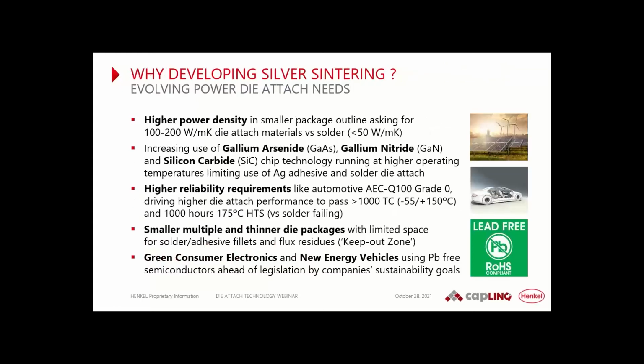So apart from lead-free, as I mentioned already, higher power density is another driver. Also the change in chip technology, moving to gallium arsenide, gallium nitride, silicon carbide running at higher temperatures. Then solder is getting marginal on reliability. And reliability, like Chris already mentioned, automotive, higher temperatures, is also one of the key reasons to go to sintering, because most solder joints cannot pass 1,000 cycles automotive. And then we indeed have also smaller packages with limited space for solder, fluxes, fillets, etc. And of course, sustainability comes in as well.